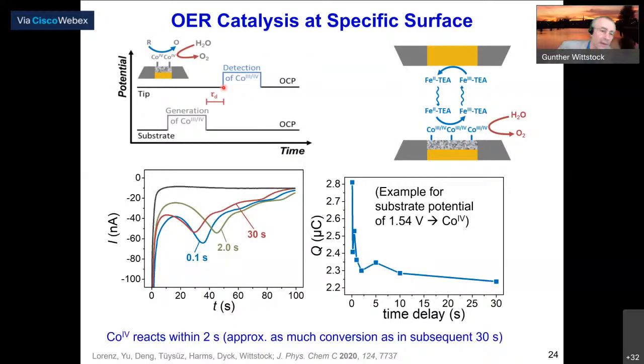But we can do more. We can make a titration experiment, but having a competing reaction. So let's assume the following. We make a potential pulse to generate a particular surface state of this cobalt oxide. Then we allow a delay time in which, for example, water could react with that state to generate oxygen, in an oxygen evolution reaction. And then after a defined time, we titrate the remaining cobalt-3 or cobalt-4 species. And then we can again calculate the charge, but now as a function of this delay time. And you see such an experiment here.